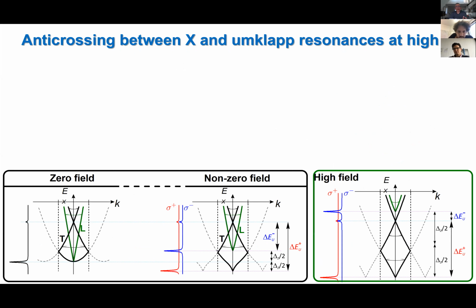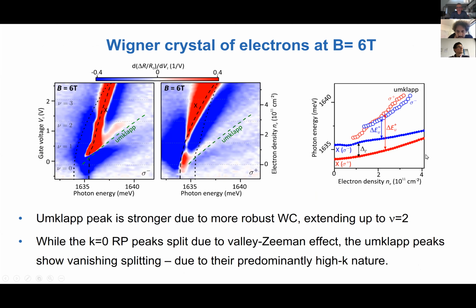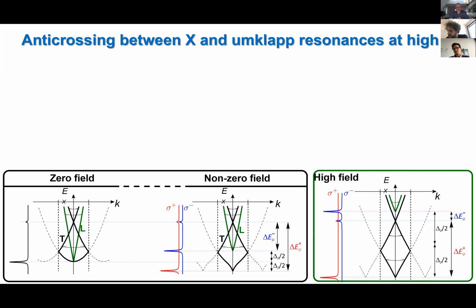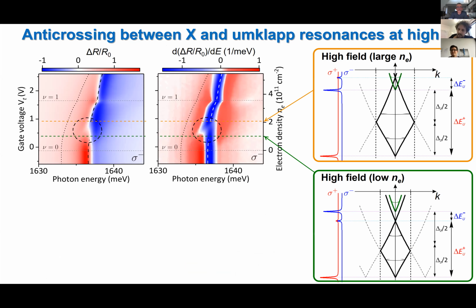Another point is that, since the features are enhanced when the two resonances are close to each other, we can ask the question: can we actually anti-cross the K equals 0 resonance with the umklapp resonance? Because the umklapp resonance doesn't depend on magnetic field, but the sigma minus resonance does. So we can, in principle, by increasing the magnetic field, start out for a given electron density in a situation where the resonance is above the umklapp. And in this case, we would expect to be able to see the resonance more strongly. And indeed, as you can see at 14 Tesla, one can even see in bare data the new resonance appearing and merging with the bare exciton resonance.